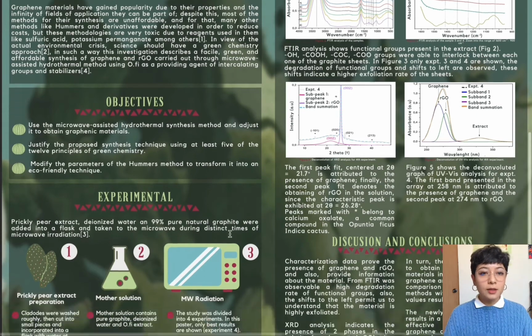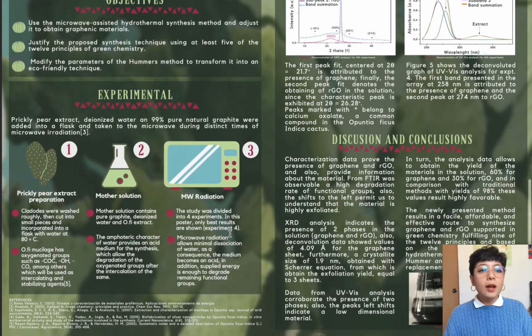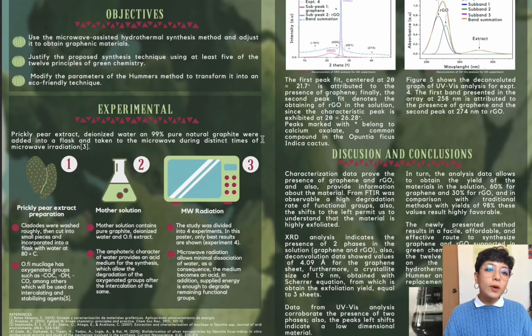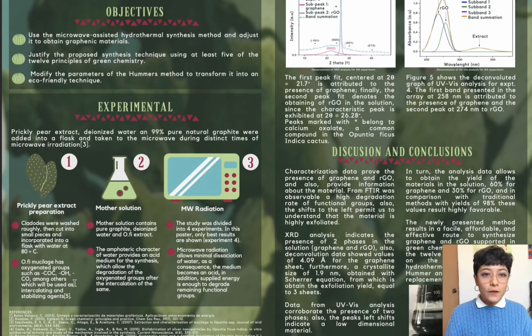Now, experimental part. Prickly pear extract, deionized water, and 99% pure natural graphite were added into a flask and taken to the microwave during distinct times of microwave irradiation. First, extract preparation. Cladodes were washed thoroughly, then cut into small pieces and incorporated into a flask with water at 80 degrees. As you might know, Opuntia ficus indica has a lot of oxygenated groups such as epoxy, hydroxyl, ketones, among others, which will be used as intercalating and stabilizing agents. This meets the first Hummers' method requirement, oxidative reagents.